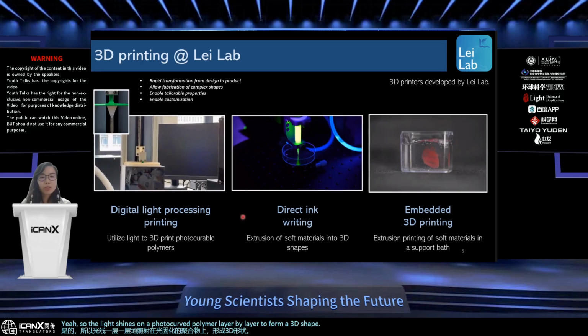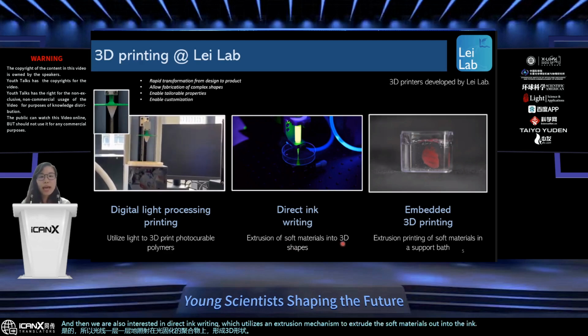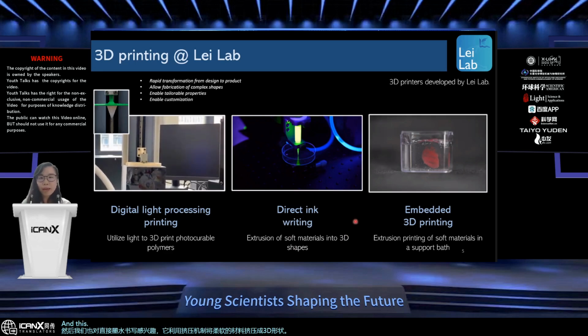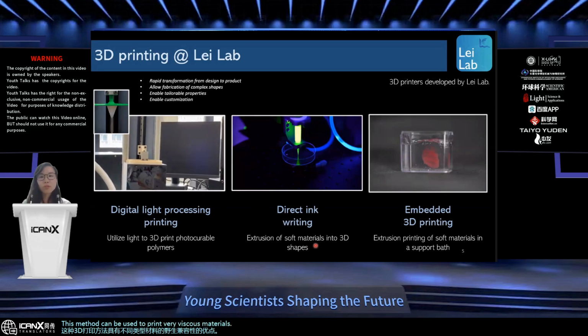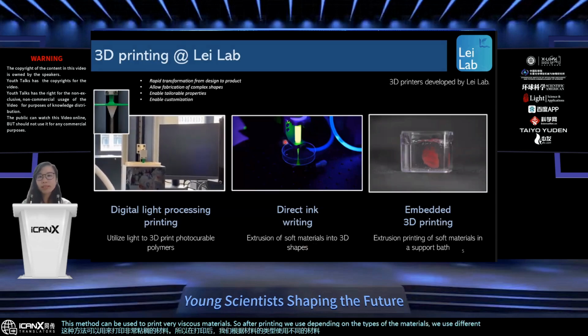And then we are also interested in direct ink writing, which utilizes an extrusion mechanism to extrude soft materials out into 3D shapes. This 3D printing method has the advantage of wide compatibility with different types of materials. This method can be used to print very viscous materials. After printing, depending on the type of material, we use different cross-linking methods to cross-link the materials.